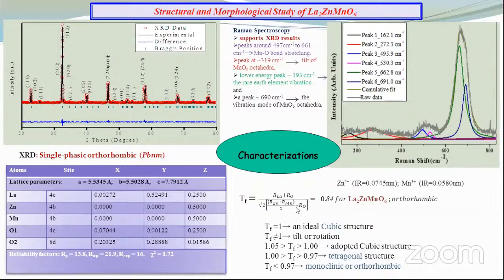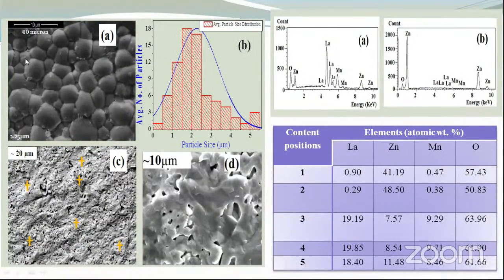And we have checked the tolerance factor, to see whether this double perovskite oxide exists or not. We found the tolerance factor to be 0.84 here. So 0.84 indicates a monoclinic or orthorhombic structure. So this also supports our refinements. And this is the SEM micrograph. There are various grains of unequal size, and nearly spherical grains are observed. The average grain size is 2.25 micrometers.